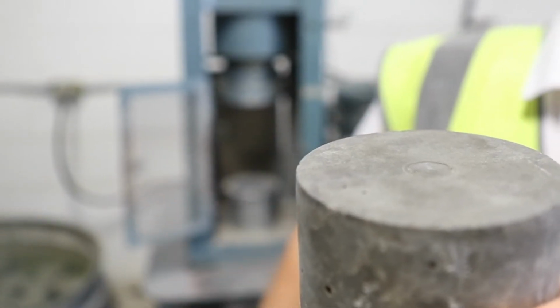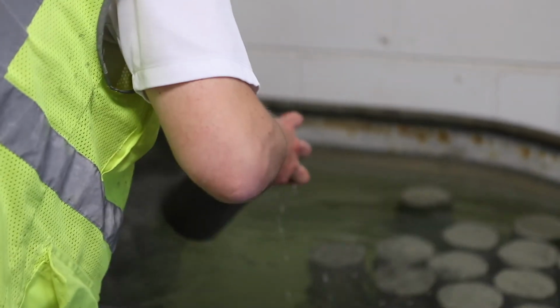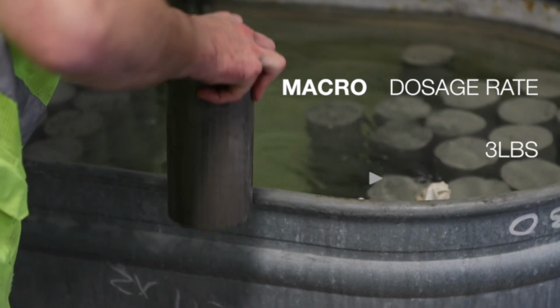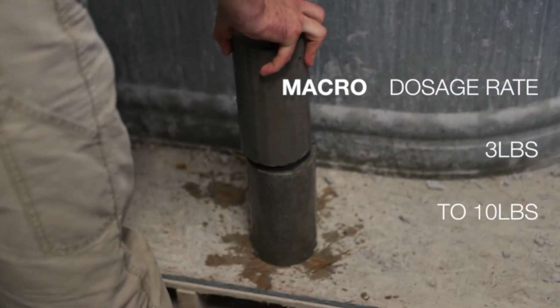How much should you use of each product? Well, the microfibers are usually dosed anywhere from a ½ pound to a 1½ pound dosage rate. Macros, they're usually dosed anywhere from a 3 pound to a 10 pound dosage rate.